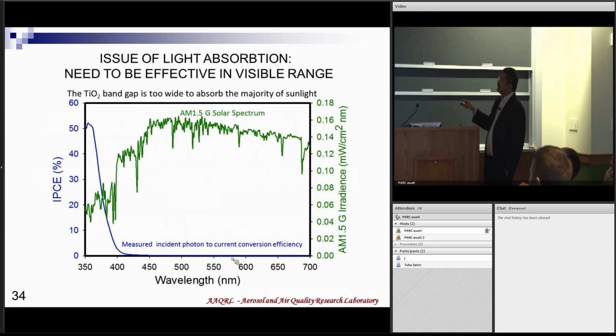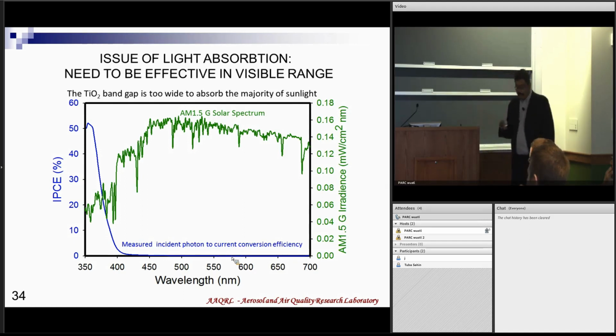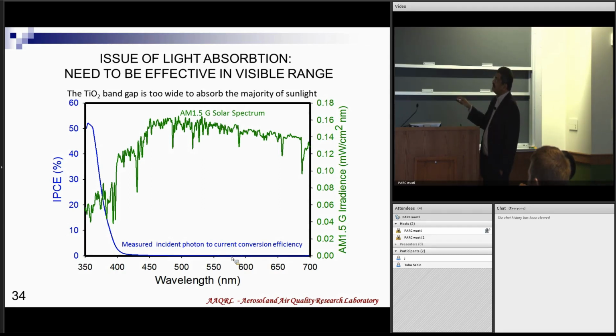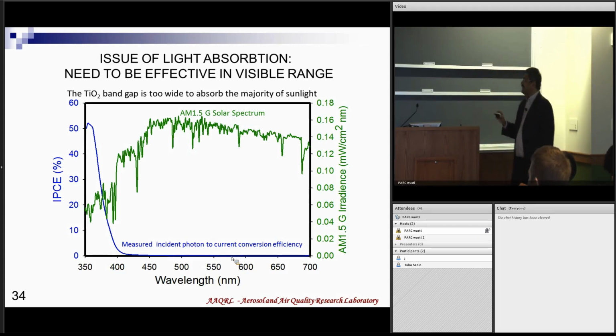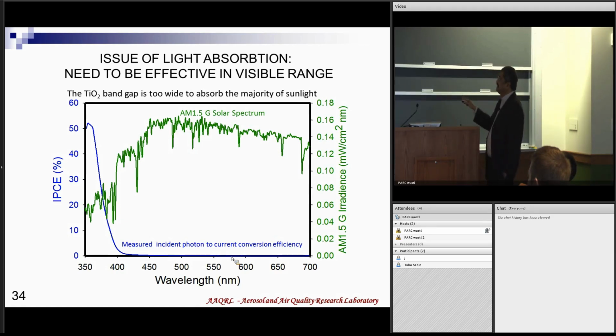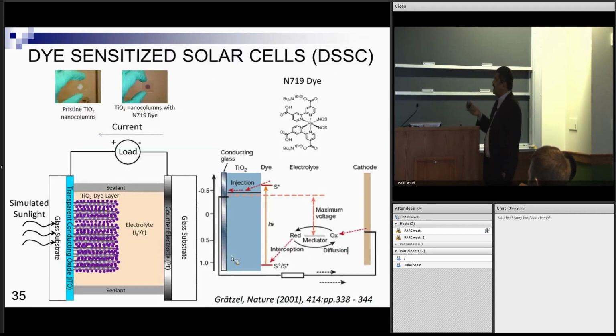And again, this shows it. This is the IPCE, it's an overall efficiency, and this is AM 1.5, air mass 1.5 irradiation as a function of wavelength. This is a standard that we typically use in the lab. So we have these solar simulators that you can test these devices, and you see that this TiO2 film is of course effective only at the low wavelengths, and by the time you come here it has zero efficiency, right? So it's totally ineffective, and you're just wasting most of this irradiation. If you could harvest it, that's great.